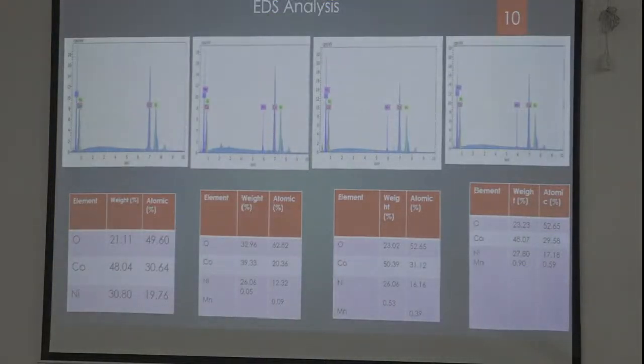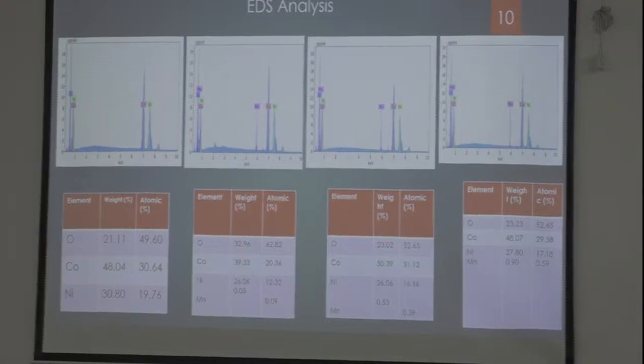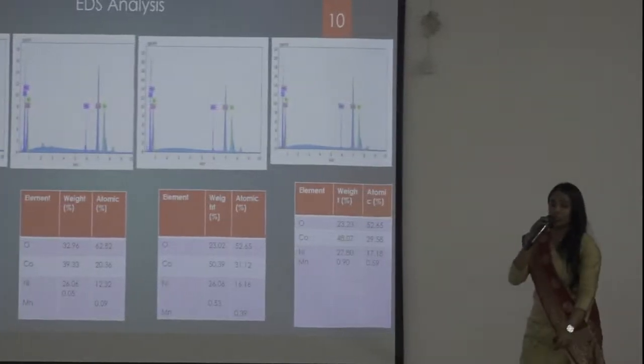This is the EDAX analysis of the material. I confirmed my elements using EDAX analysis, and also calculated the weight percentage and atomic percentage of each element for nickel cobalt oxide and the three ratios of manganese doped nickel cobalt oxide.